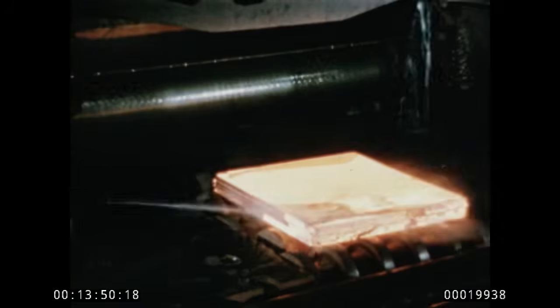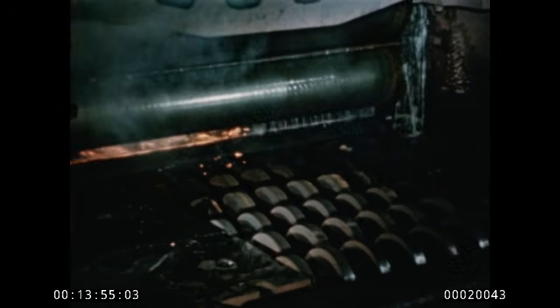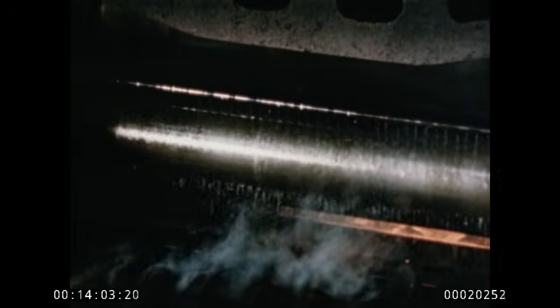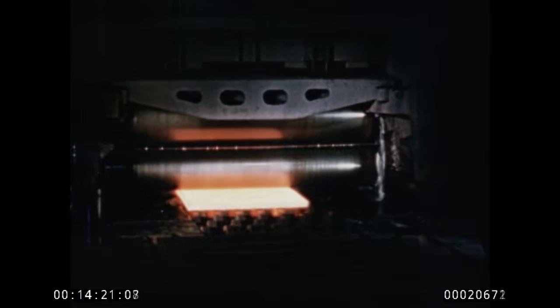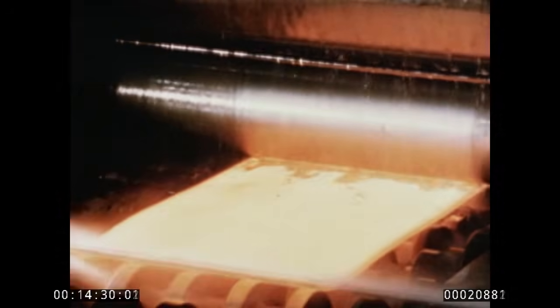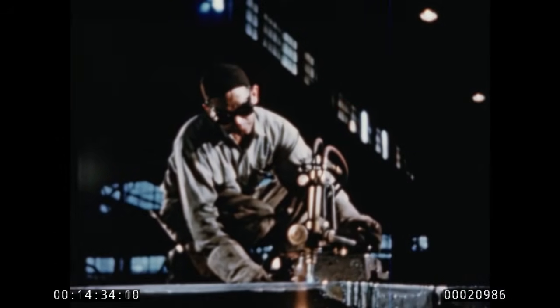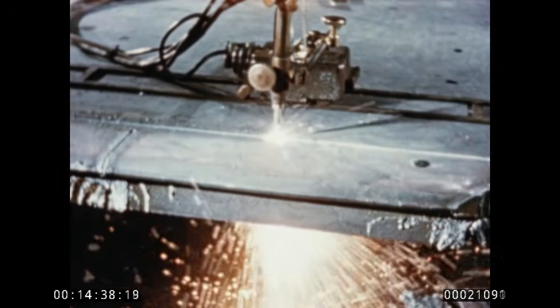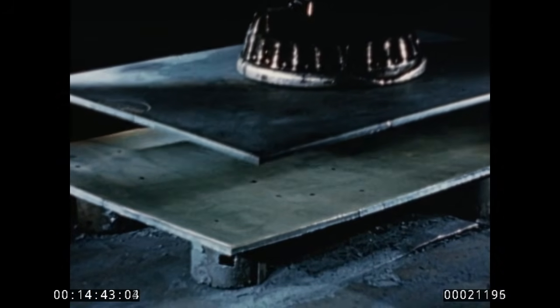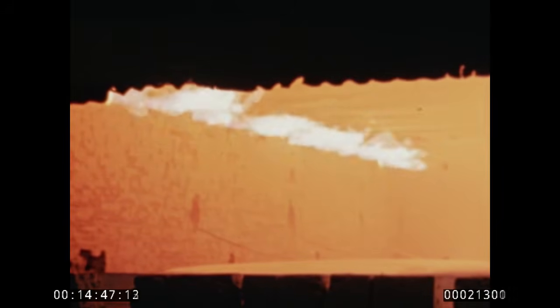At our big rolling mill, you can see heated assemblies ready for the rolling that reduces them to plate thickness and pressure bonds the cladding and the backing plates. Our mill can roll clad plates up to 178 inches wide and other plates up to 195 inches wide, and it's kept mighty busy. Then the sandwich is flame cut inside the welded perimeter and separated into 2 plates. After that, we heat treat our stainless clad plates to increase their corrosion-resistant qualities.